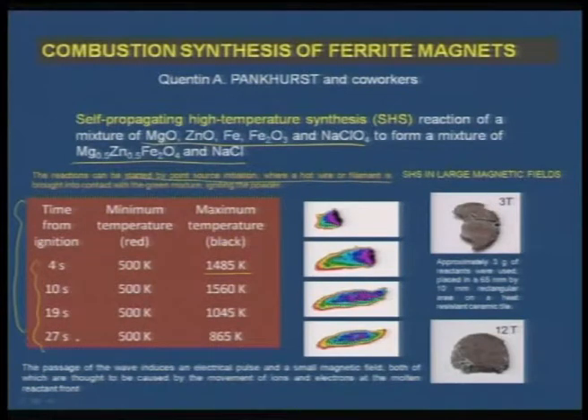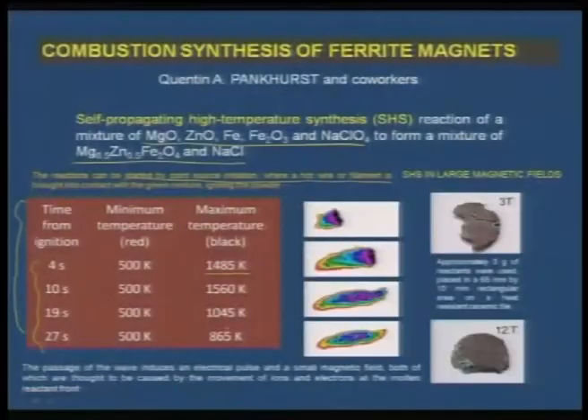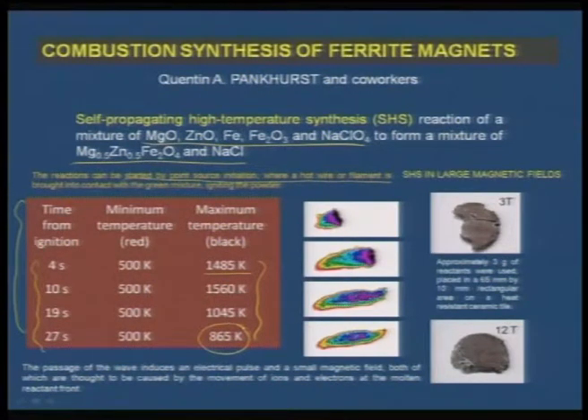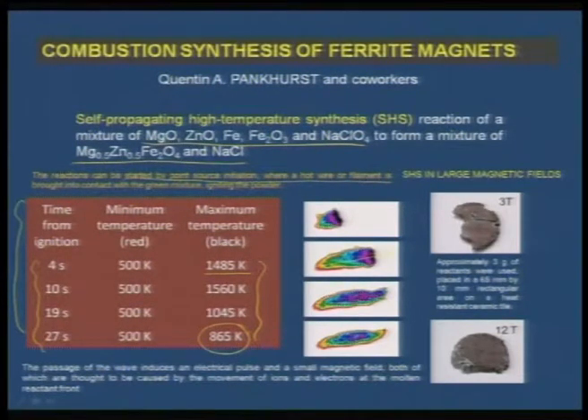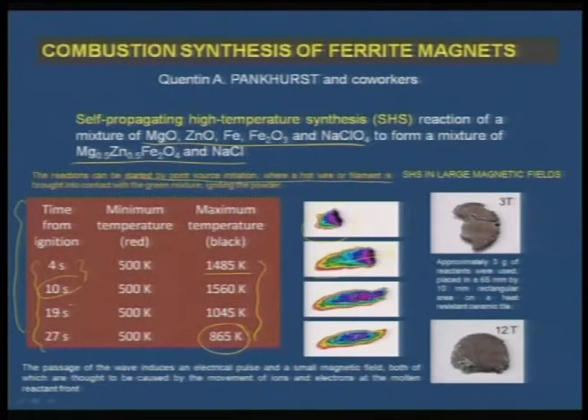The reaction is self-propagating — once initiated it propagates on its own and completes the reaction without sustained external heating. From the temperature profile, by 27 seconds the combustion is over and cooling begins. The IR (infrared) image clearly shows how temperature propagation occurs from low to high, with maximum temperature hit between 4 and 10 seconds, followed by cooling.